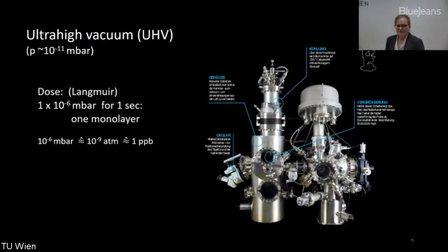The surface science method uses very well controlled conditions, typically ultra-high vacuum, at pressures of 10 to the minus 11 millibars. The experiments are conducted in stainless steel ultra-high vacuum chambers that are sophisticated, expensive, and cumbersome to use. But the reason is that everything out in air will be dirty.